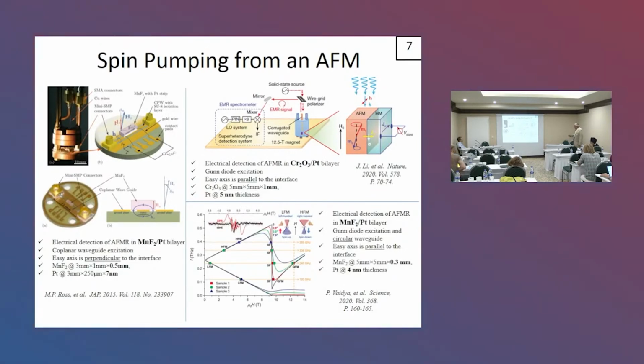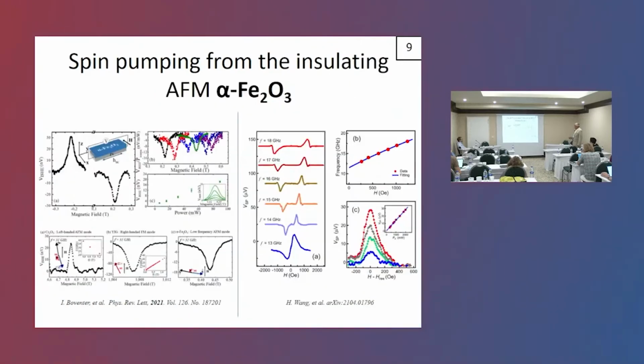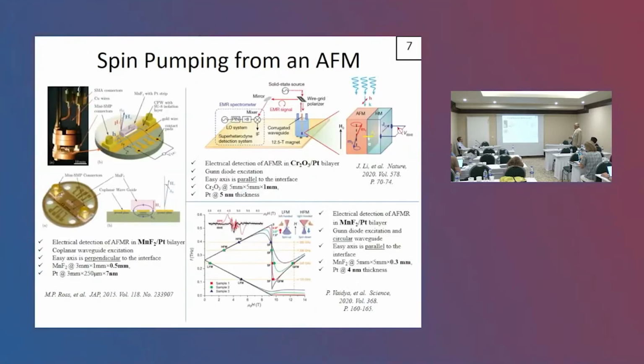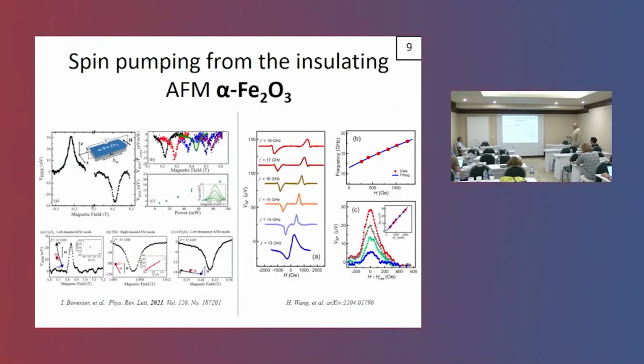It was shown experimentally that if you put an antiferromagnet in contact with a ferromagnetic material and you excite a ferromagnetic resonance in the ferromagnetic material, there will be a spin pumping into the antiferromagnet, and using the inverse spin Hall effect, you can actually detect the signal. And that was demonstrated both in chromium oxide, in manganese fluoride, and in hematite.